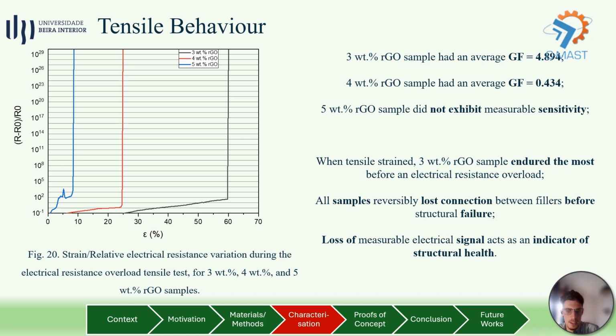The last electromechanical test consisted of tensile straining the samples until the structure lost its interconnections, and a reversible behavior was observed where the samples returned to their normal state when relaxed. In addition, the loss of the electrical component always occurred before the material's structural failure.